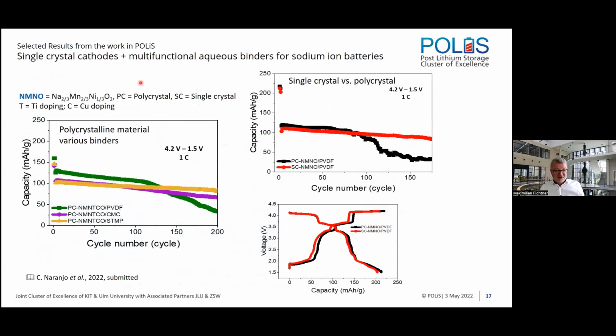And here are also related results. We have here a polycrystalline manganese nickel oxide with various binders. Yeah, so here the green one is the PVDF, the other ones are CMC and the phosphate binder. And here we have a comparison of single crystal and polycrystalline material. And this is the charge and discharge curve related to that.